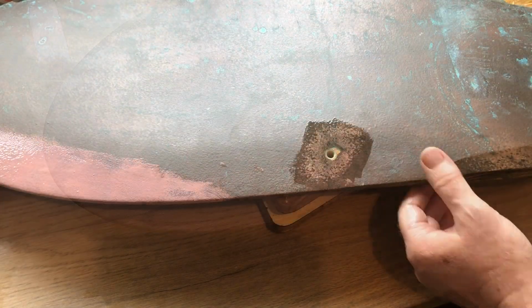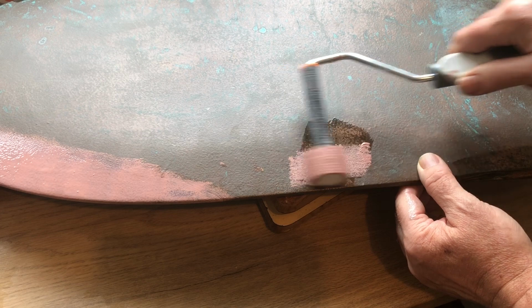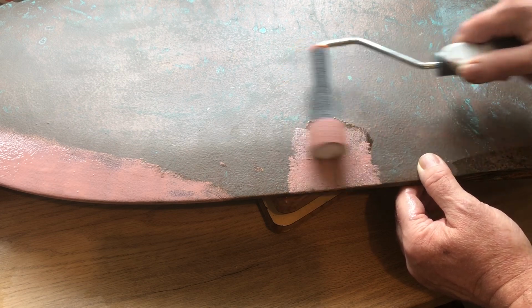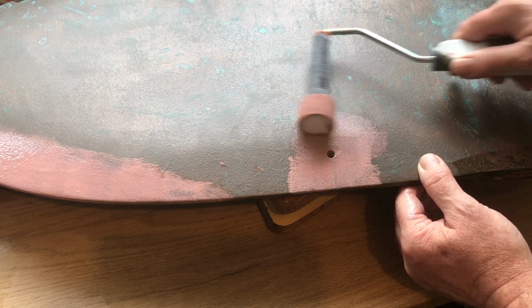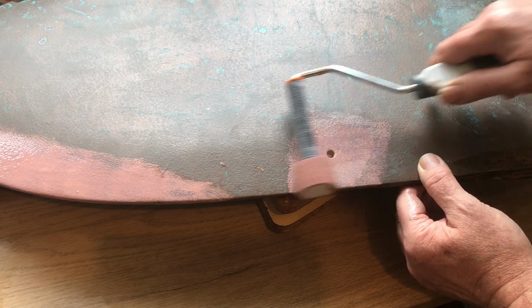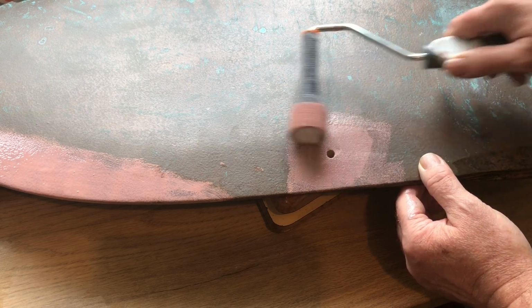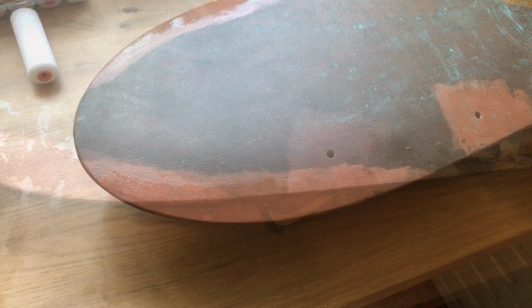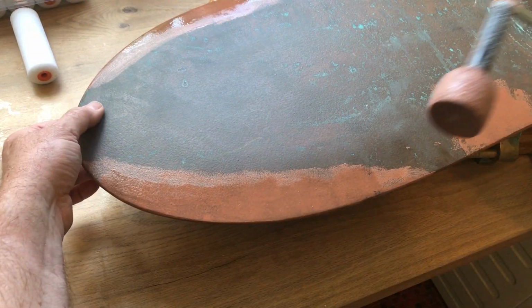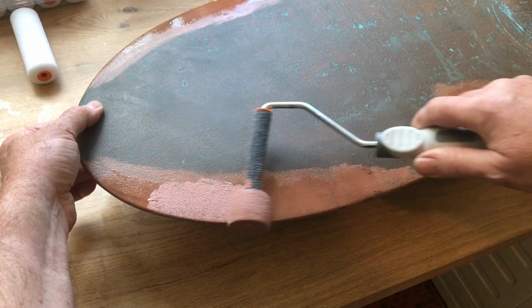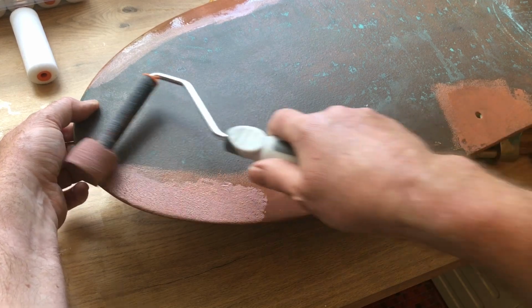It's important to apply Coppercoat just beyond the edge of the first resin and hardener coat. You don't want to leave any of the first coat exposed to the elements because it contains no copper and therefore has no antifoul capability. I applied 4 coats. Coppercoat recommend 4 to 5. Each coat was applied wet on tacky, and I cleaned the jar and tray and used a fresh roller with each coat.